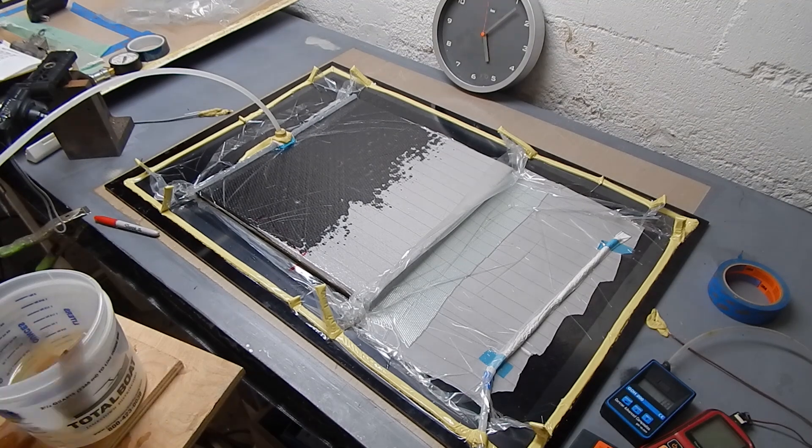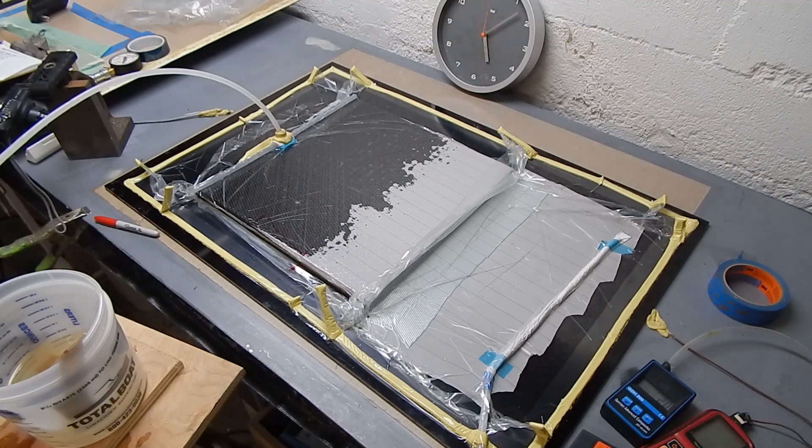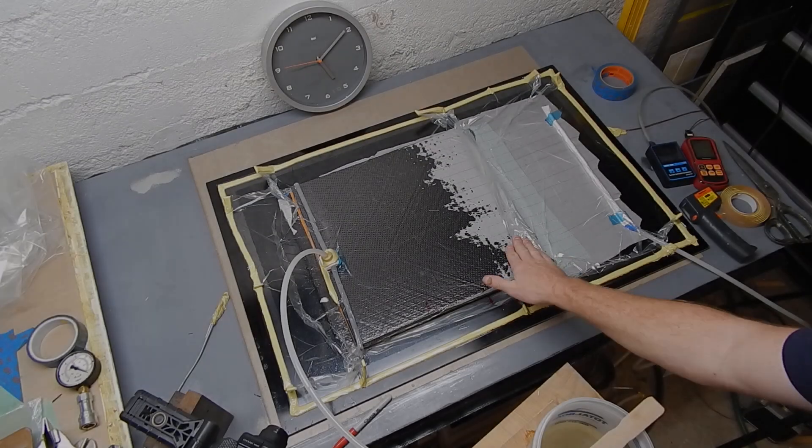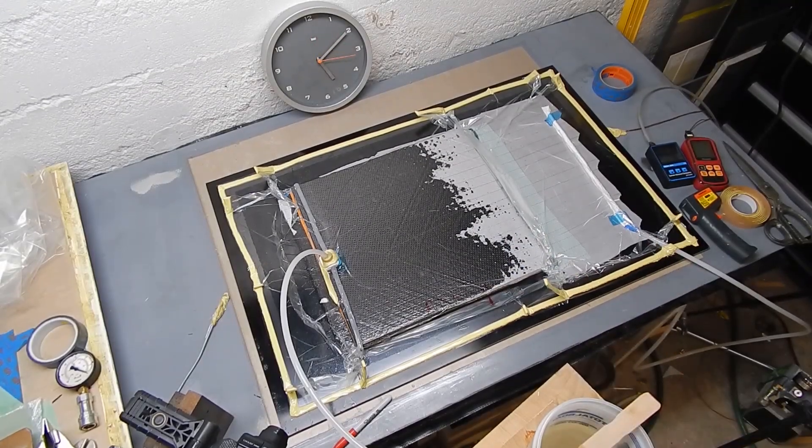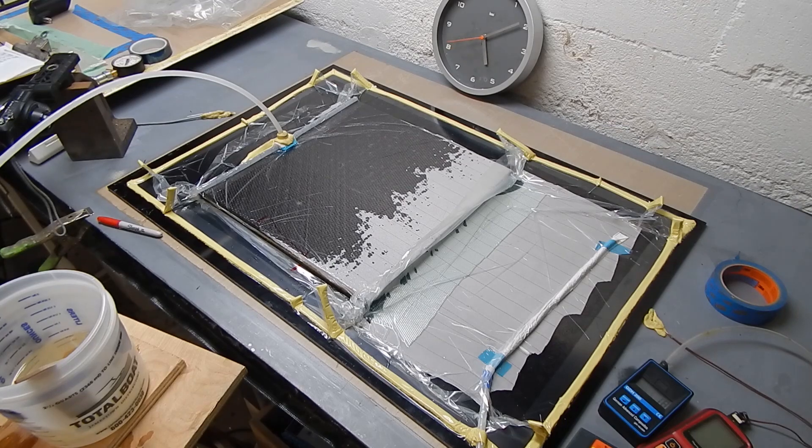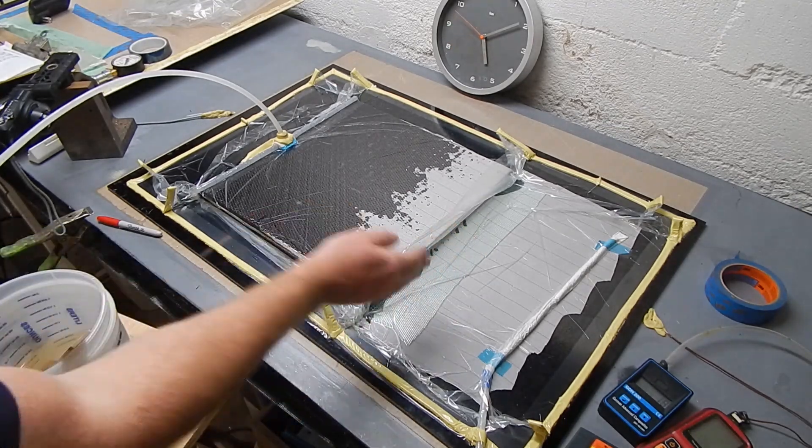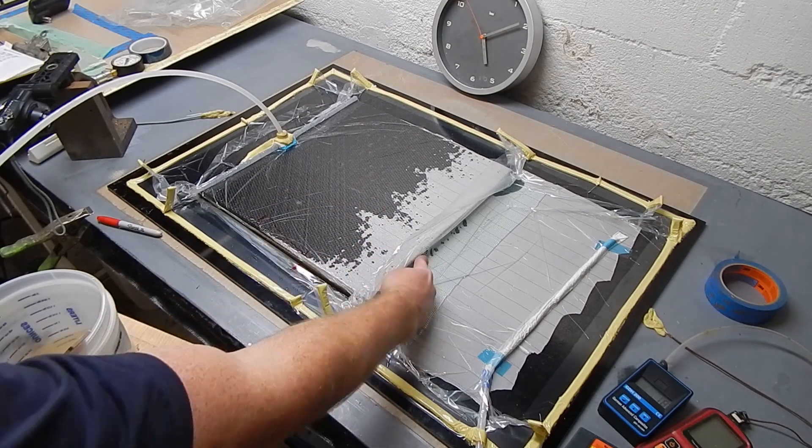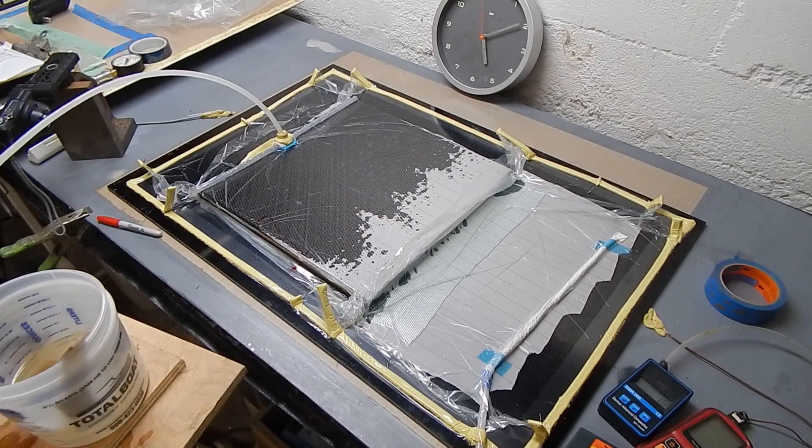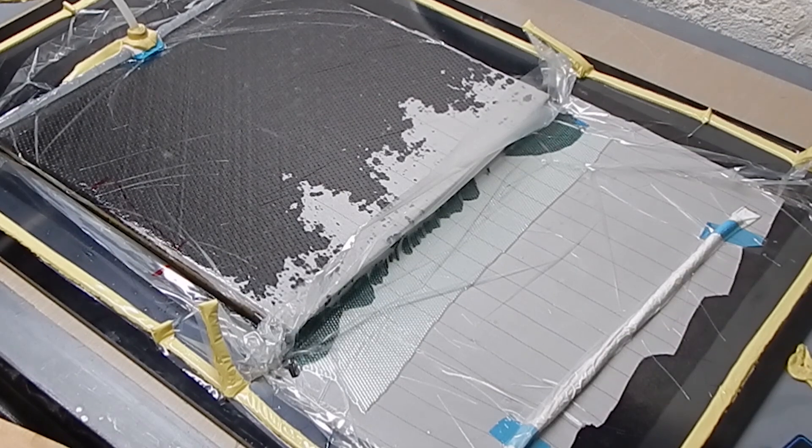So as it fills here, at the bottom it's starting to poke through the resin there on the outlet side, and as I feared, it was not reaching the end at the same time. So that little piece of green flow I put in while laying it up should allow the air to escape out of that top skin. See the air there coming out.